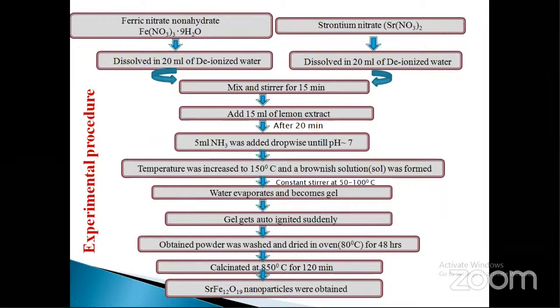I have chosen lemon extract as a capping agent, and 15 ml of lemon extract was added. After continuous stirring for 20 minutes, 5 ml ammonia was added dropwise until the pH became neutral, and the temperature was increased to 150 degrees Celsius, and a brownish solution was formed. After constant stirring, the water evaporates and it becomes a gel, and the gel autoignites suddenly. The obtained powder was washed and dried in an oven at 80 degrees Celsius for 48 hours, and the obtained samples were calcined at 850 degrees Celsius for 120 minutes, and SrFe12O19 nanoparticles were obtained.